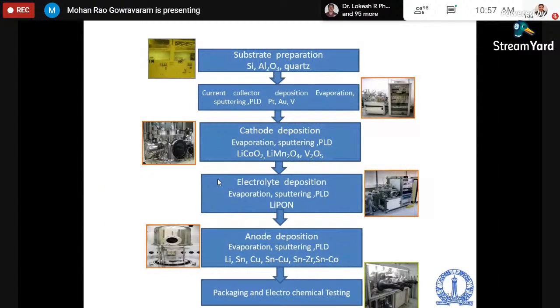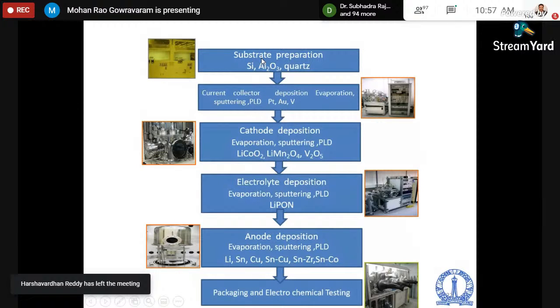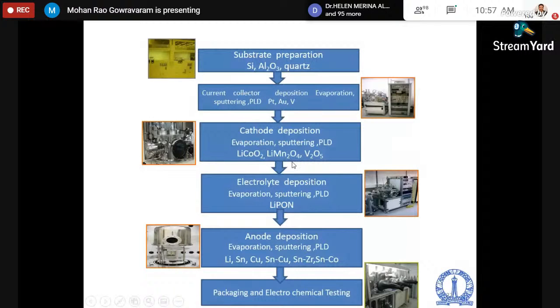So with this, if you try to develop thin film batteries in your laboratory, like any other materials research, you have to undergo all these steps. You start with the preparation of your substrate. That means you clean your substrate properly, and then you have a deposition chamber where you deposit a current collector, then another deposition chamber where you have the cathode layer deposition, then electrolyte deposition, then anode deposition, and finally the packaging and electrochemical testing. So these are all several steps that are involved in developing a thin film battery. This is on the fabrication side.